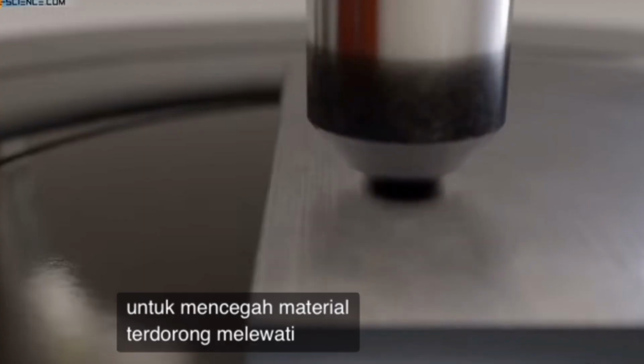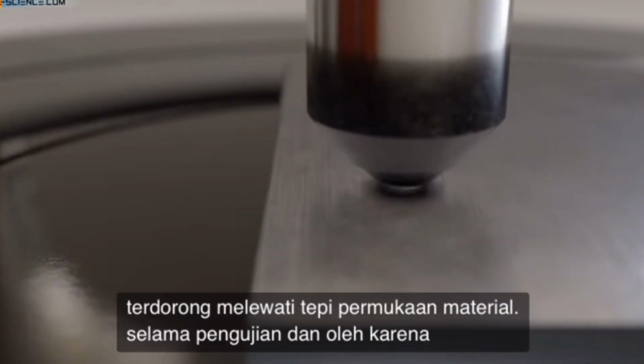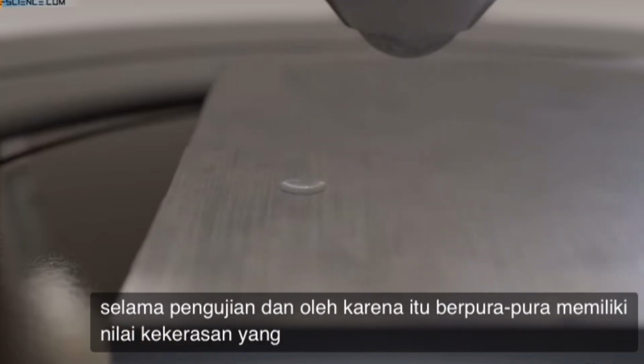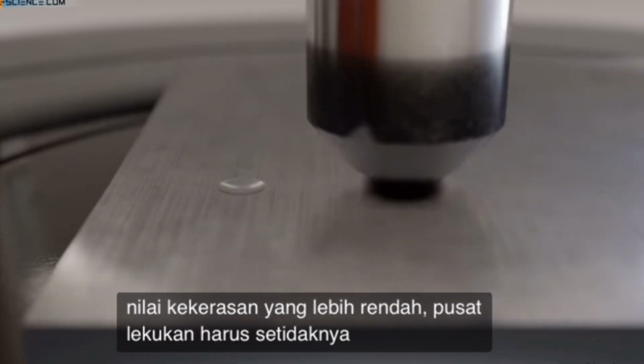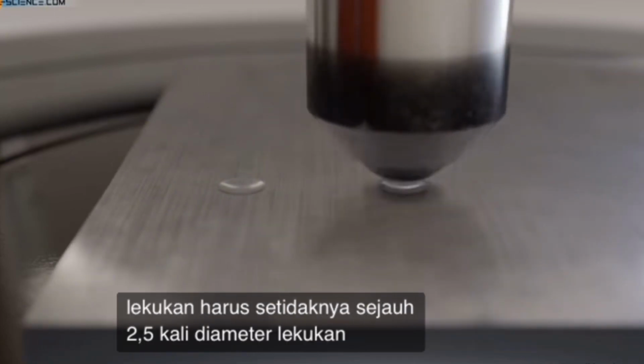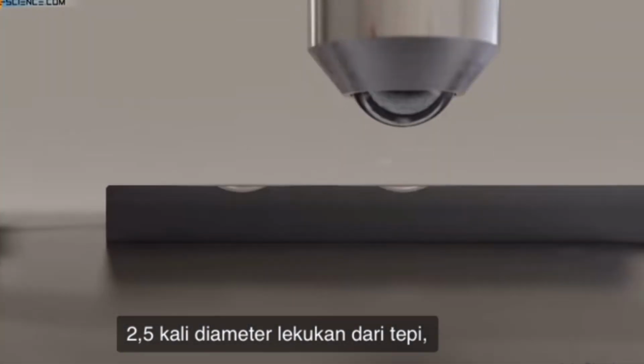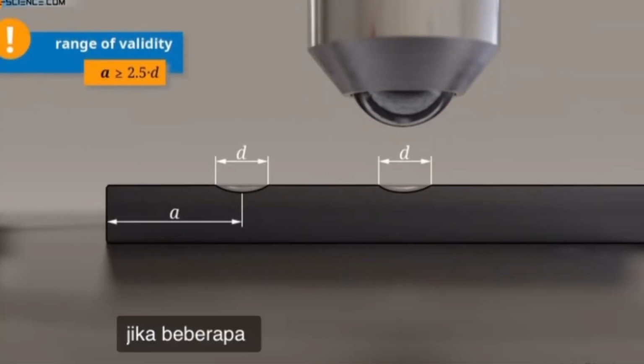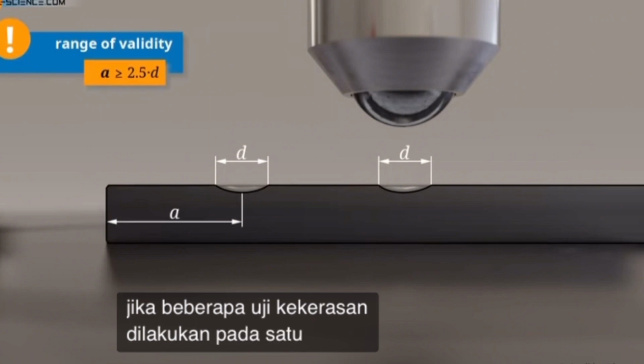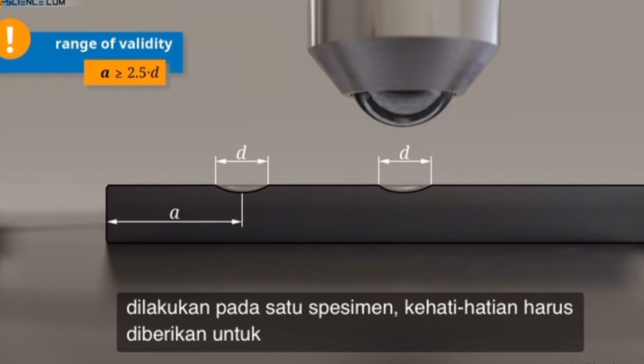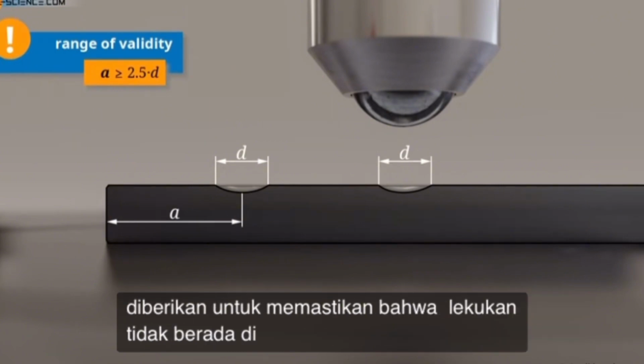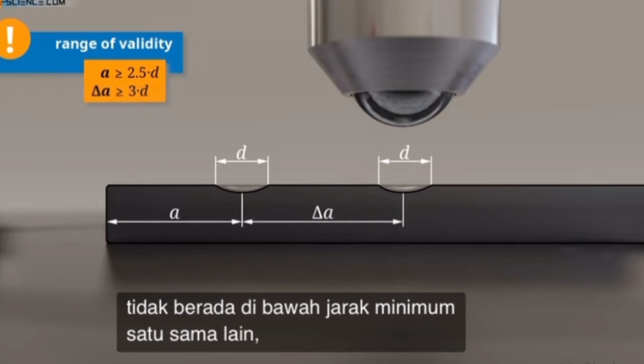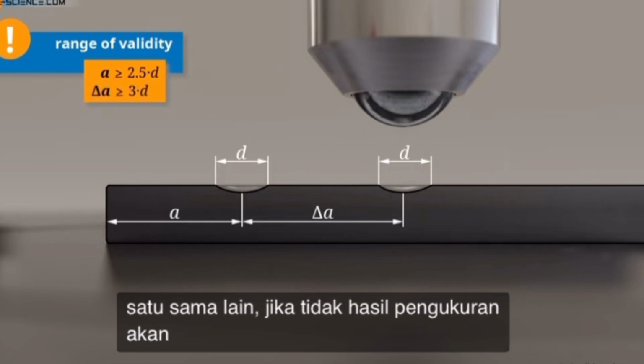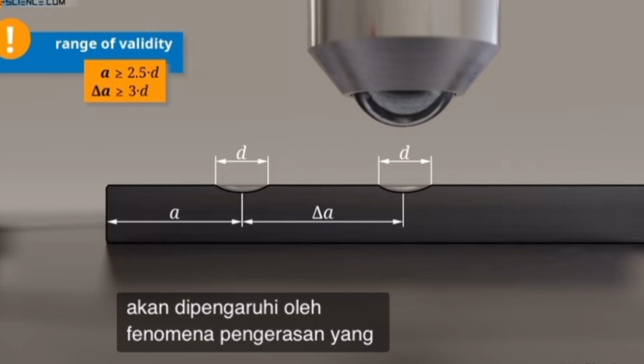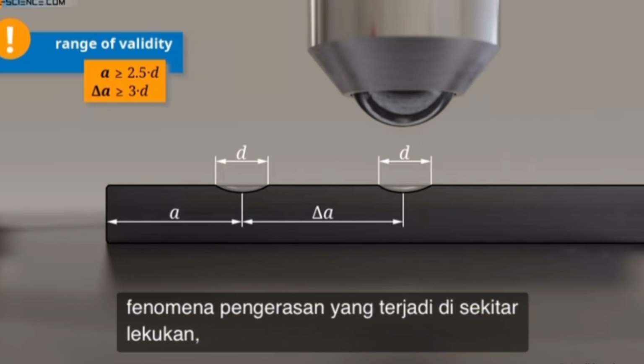To prevent material from being pushed over the edge of the specimen during testing and therefore pretending a lower hardness value, the center of the indentation should be at least as far from the edge as 2.5 times the diameter of the indentation. If several hardness tests are carried out on one single specimen, care must be taken to ensure that the indentations do not fall below a minimum distance from each other. If not, the measurement result would be influenced by hardening phenomena occurring around the indentations.